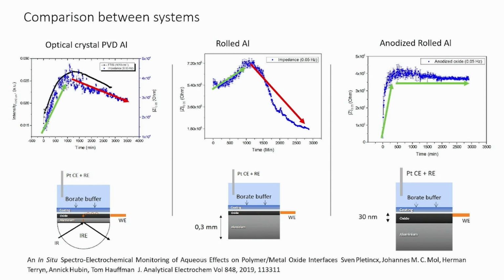Why is that interesting? Because then you can go to conventional substrates. This is, for example, the PVD aluminium metal. This is the rolled aluminium metal, which was prepared in the same way, with the same pre-treatments. And then you can change pre-treatments, and you can use your impedance measurements to follow the bonding system as a function of time, which we are doing at the moment. So the impedance allows you to work on more complex substrates.